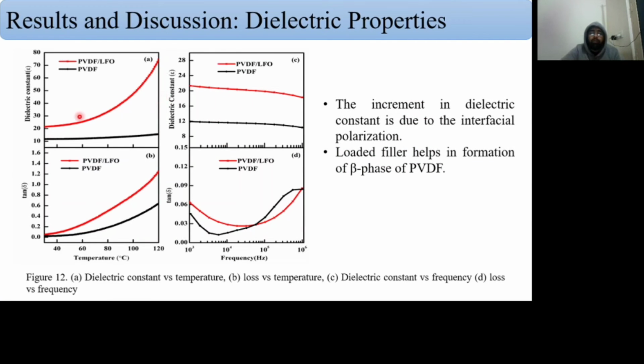Dielectric properties. In this figure, we can see the dielectric constant is increased with the loaded filler. This happened due to interfacial polarization. In the dielectric constant versus frequency plot, we can see the dielectric constant is decreased with increasing frequency. This can be attributed to the interfacial polarization, because at higher frequency the interfacial polarization is less dominating compared to low frequency.